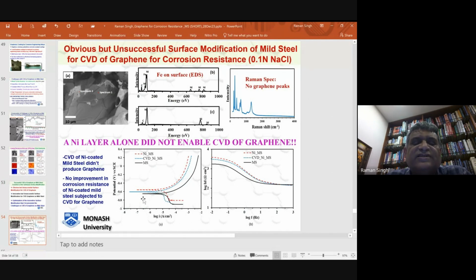So reason is very simple. The carbon that you produced because of splitting of hydrocarbon during CVD, that carbon will not stay in nickel layer. It will continue to diffuse into mild steel. Mild steel also has huge solubility of carbon. So you lose carbon that you require for graphene development. And as a result, no graphene was developed.